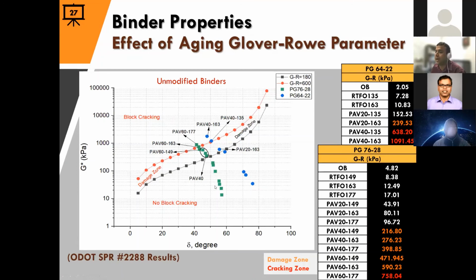But if you look at it, here is what's happening. As you keep oxidizing the material, you start moving up and up. And see, if you RTFO age it at 163 and then 40 hours of PAV, now you are finally in the range of block cracking. This is one of the materials. These plots are for 64-22, and these points are all for 76-28.